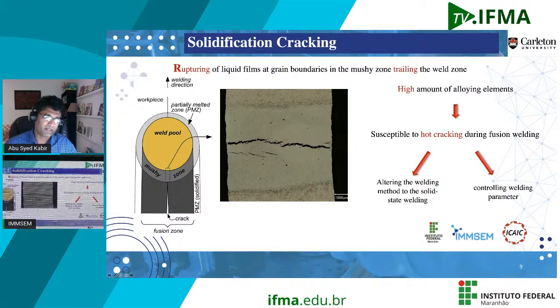Due to the presence of this high amount of alloying elements and formation of so many different kinds of phases during the solidification, some of the phases have very low melting temperature compared to others, like let's say eta phase that I showed you in the previous slide has melting temperature about 420 degrees Celsius compared to aluminum itself, which is approximately 650 degrees Celsius.